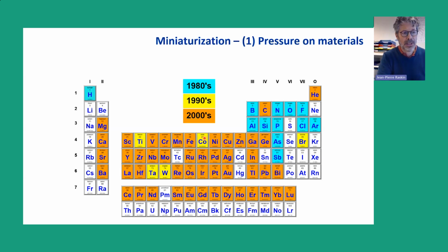But in 2000 there was a big shift, a big change in the microelectronics industry. You can see here highlighted in orange all of the materials that are used today in microelectronics to keep track of Moore's law. I don't have the time, nor the expertise, to explain all of these materials, but you can recognize germanium, which is mostly used for straining the channel and increasing the carrier mobility. You can also see hafnium oxide. It's now the most popular high-K dielectric used for the gate stack.